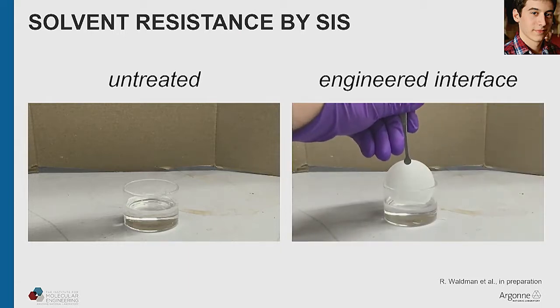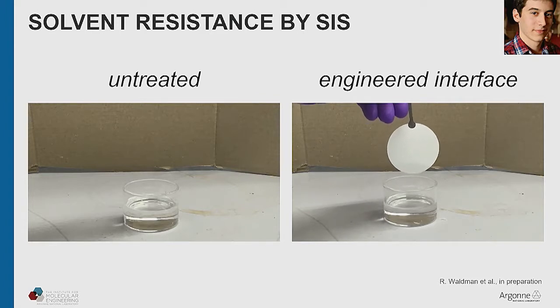I love that video. So you don't want that to happen. So now we take that exact same membrane and we do SIS on it. So now we're going to penetrate those polymer fibers with inorganic material, which has solvent resistance. And you can see you can now take that same membrane, put it into the same solvent, and it survives just fine. Now, that was a quick dip, to be honest. If you left it in there, it would eventually dissolve. But in most cases, you're not dealing with a situation where you're sitting in pure solvent either. Usually, you're dealing with dilute solvent situations, and the lifetime can be dramatically extended this way.